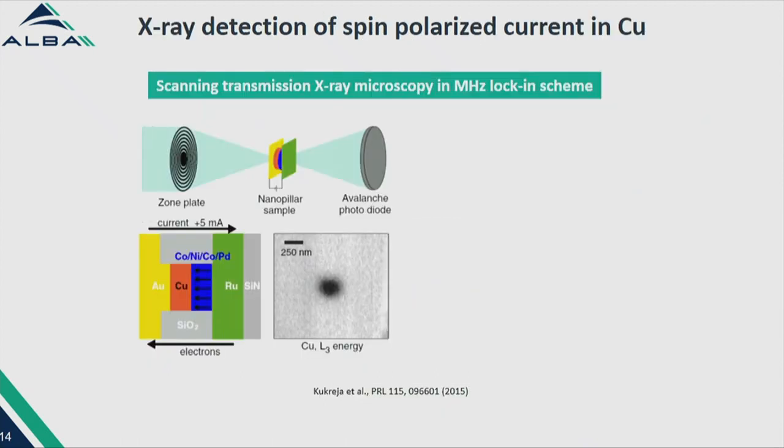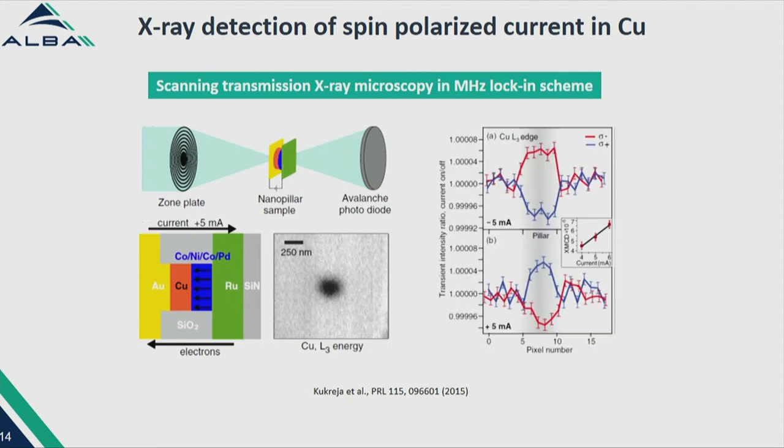And also, as Professor Hoffman has shown, it is also good that already in the recent past, a group has shown that it is not impossible to measure spin accumulation in copper. This is a very different experiment because it's a spin injection from a ferromagnetic material in transmission geometry, but at least we know the order of the effect is 10 to the minus 5. It's difficult, but not impossible.